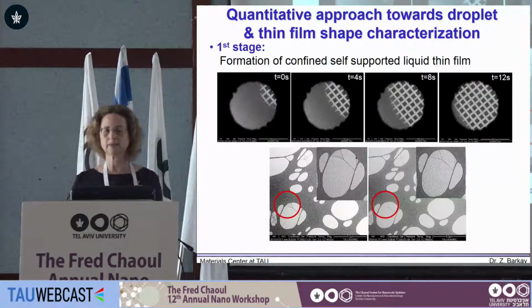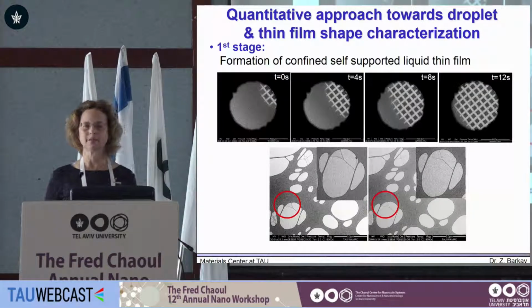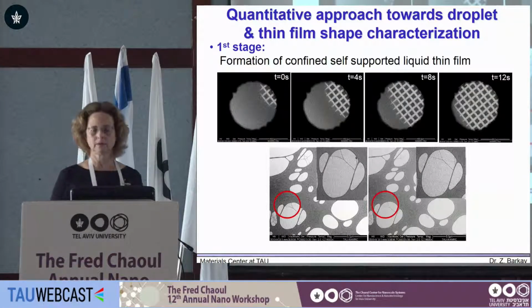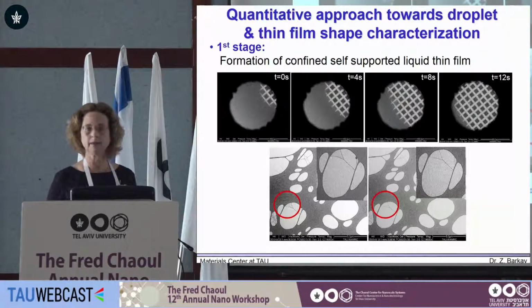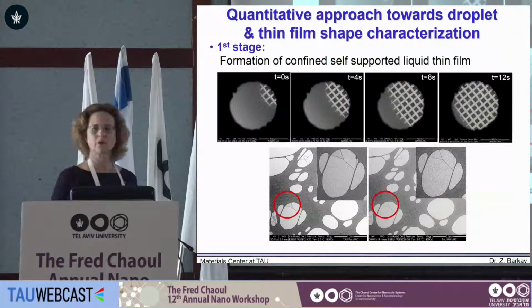So if you compare it to the situation before putting the drop, you can see the difference here. It means the trapping of liquid films still occurs, and it could be done in sizes of around 1 micron, at least at one dimension.